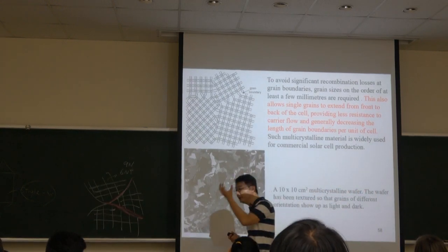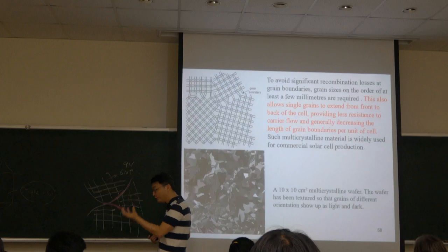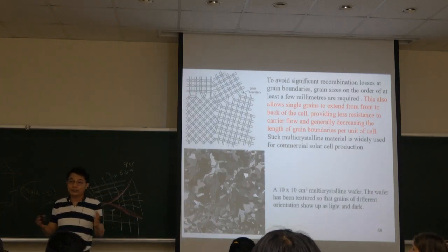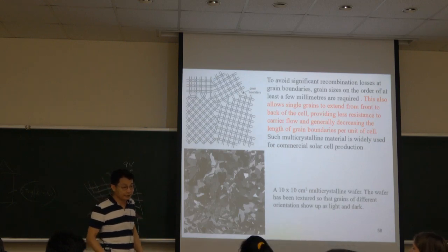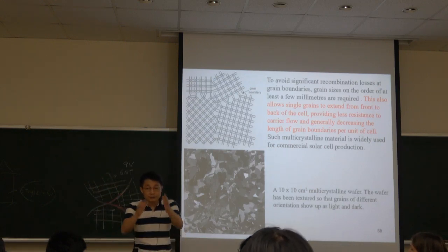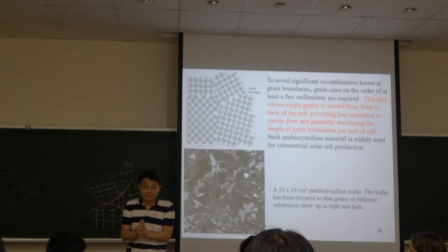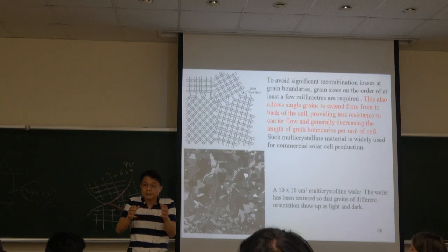When you increase the temperature to about 1,400, that is the molten state, right? So cooling to the solid state of the silicon, the cooling rate is quite important, right? You can reduce the cooling rate in order to get the higher grain size, right?